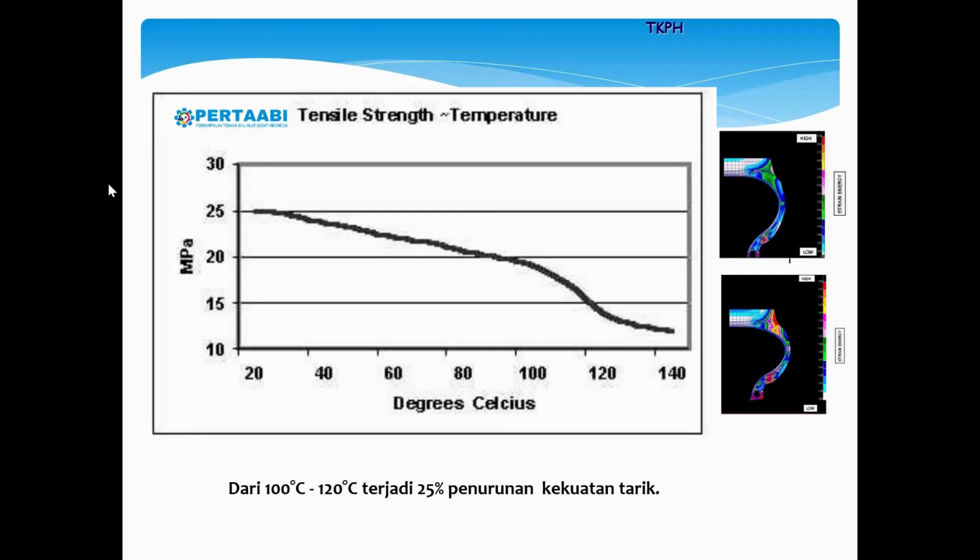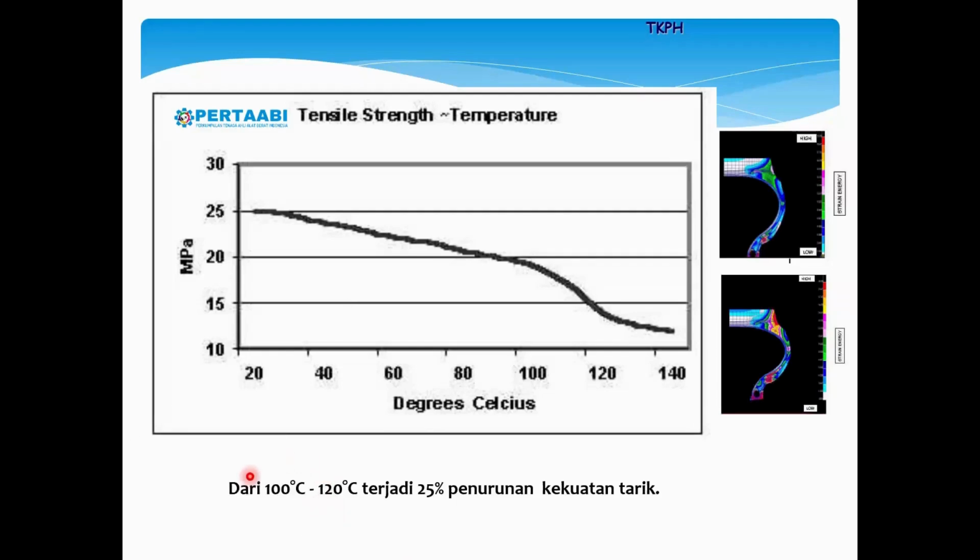And in SAE it is also mentioned that as long as the temperature is not until 104, the tire is still safe, lower than that. So this is already a critical operating point, but not melting yet. This is mentioned in SAE.